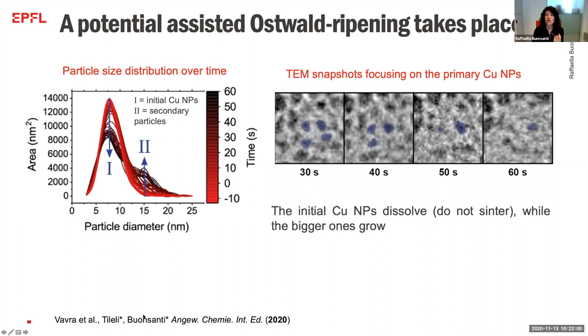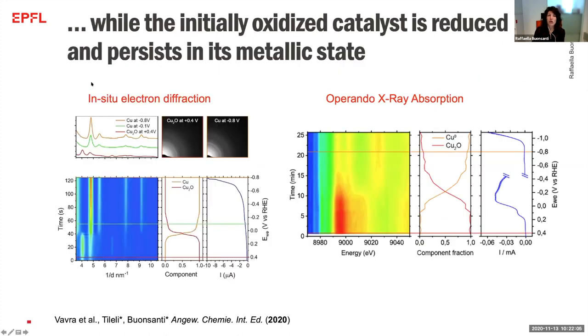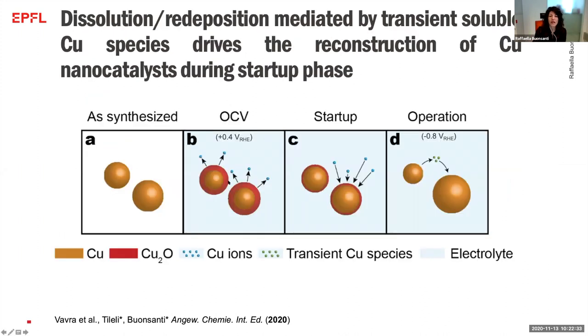And this dissolution in solution is not really straightforward to understand, because what the combination of in situ electron diffraction and operando X-ray absorption showed is that at the beginning, as we put our catalyst in the electrolyte, the catalyst is in an oxidized state. But as we apply the negative potential that is needed for the CO2 reduction, the copper reduces. So basically we have an Ostwald ripening-like process while copper is in a reduced state. So this is quite intriguing. We basically highlighted in the end the role of this oxide in an initial dissolution of the catalyst.